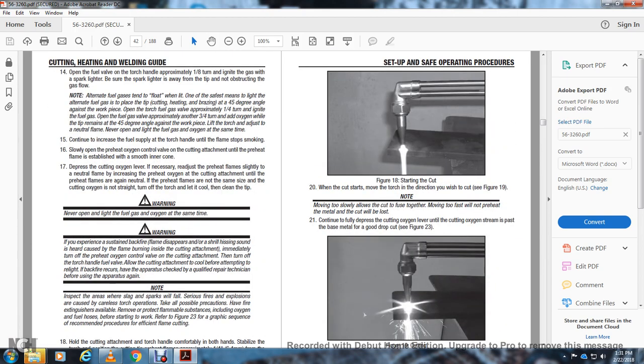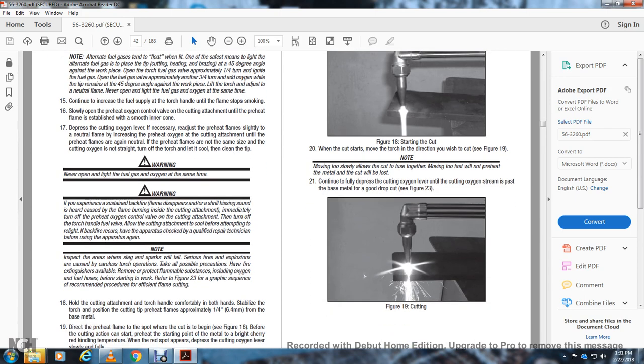20. When the cut starts, move the torch in the direction you wish to cut. See Figure 19. Note: moving too slowly allows the cut to fuse together. Moving too fast will not preheat the metal, and the cut will be lost. Continue with full depression of the cutting oxygen lever until the cutting oxygen stream passes through the base metal for a good drop cut. Figure 19 shows the cutting.